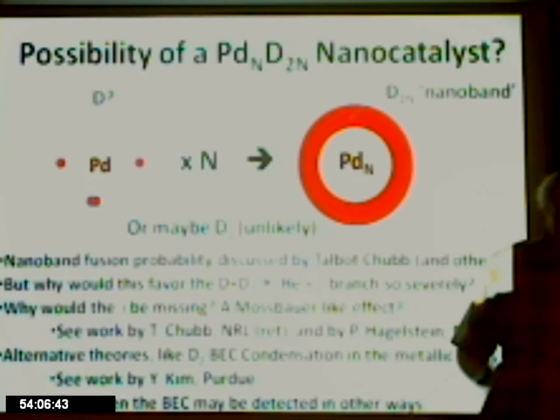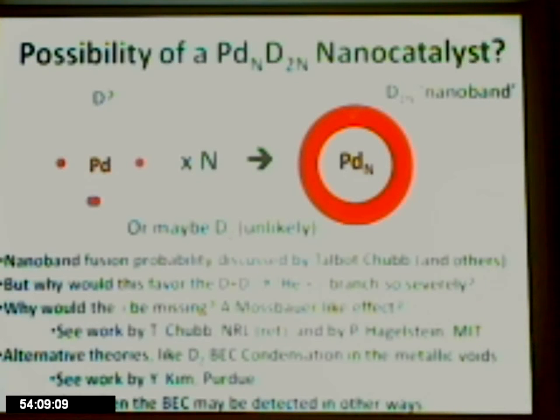Because, I should have mentioned, all these measurements, including at Naval Research Labs, on the excess heat from the palladium nanoparticles, and the results that have been seen at Kobe, Japan, by Kitamura's group, not all of them have looked for particles being emitted. None of them have seen it. So the gas diffusion loading nanoparticles have not shown a particle emission like you'd expect to see. Interestingly enough, ion bombardment in palladium has. And there have been occasional reports of particle emissions in other systems.